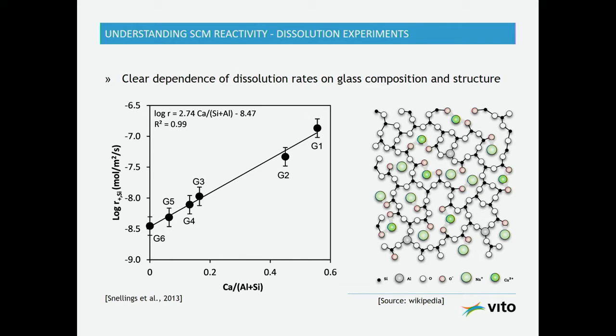If we calculate these dissolution rates and we then compare them, so these are the calculated dissolution rates here on a log scale, and then we compare them to the chemical composition. This means actually the glass structure as well behind. Then we can see a clear correlation between the calcium content for very typically blast furnace slag type of glasses. We see very high dissolution rates or higher dissolution rates, and almost an order of magnitude lower, we see the dissolution rates for silica-rich glasses.